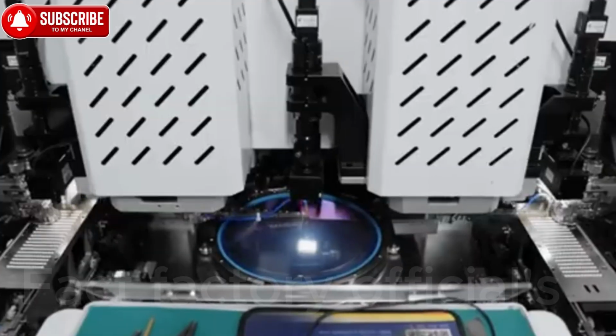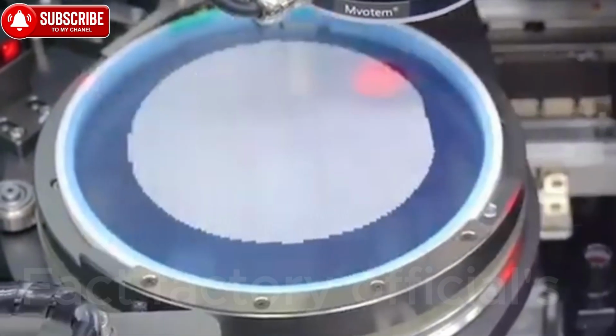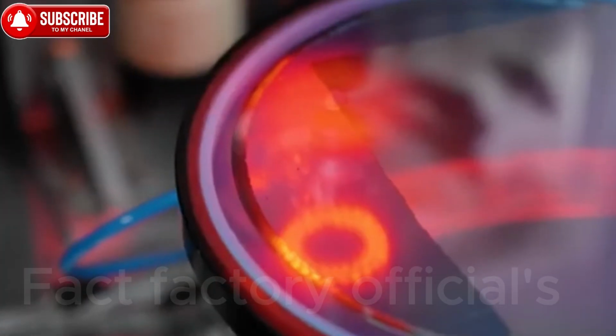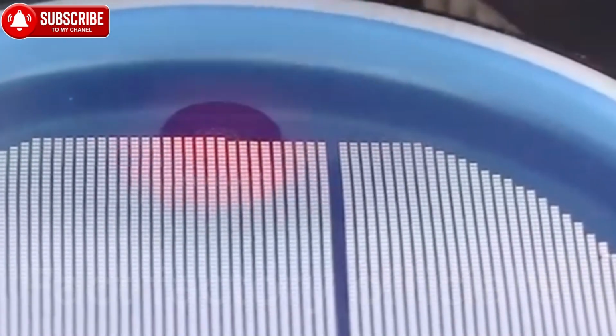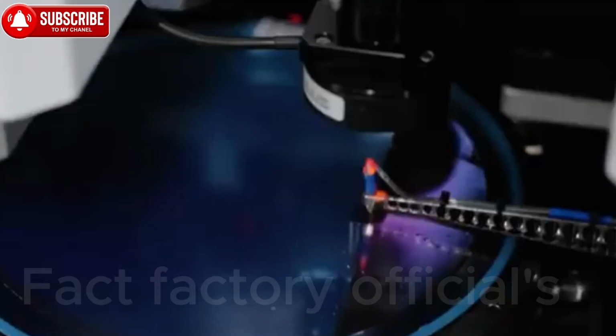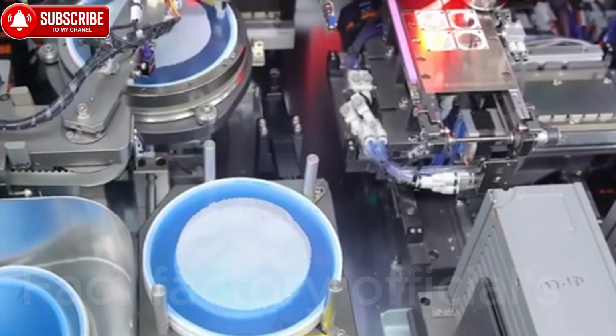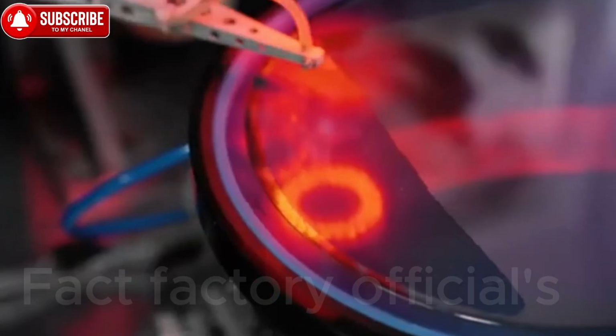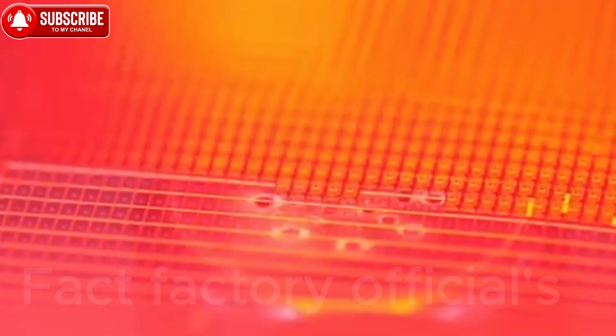Once the expansion process is complete, the film carrying the evenly separated chips is transferred to an automated pick-and-place system, ready to enter the die bonding stage. Die bonding. Each microscopic LED chip is fixed onto a metal lead frame consisting of two terminals, the positive anode and the negative cathode. An automated die bonding machine dispenses a precisely controlled dot of thermally conductive adhesive onto a designated position on the lead frame. This adhesive plays a dual role. It securely anchors the chip in place while also providing an efficient path for heat dissipation. As a result, both the volume of adhesive and its placement must be accurate down to individual micrometers.